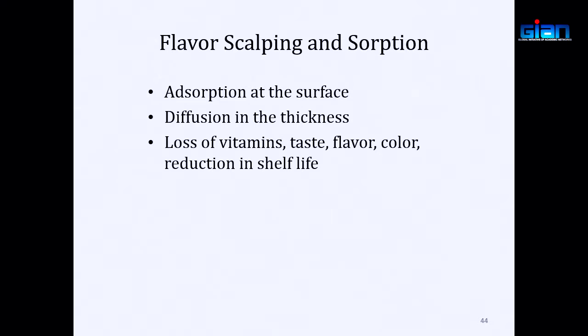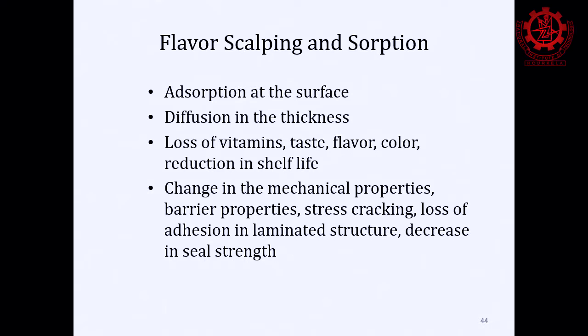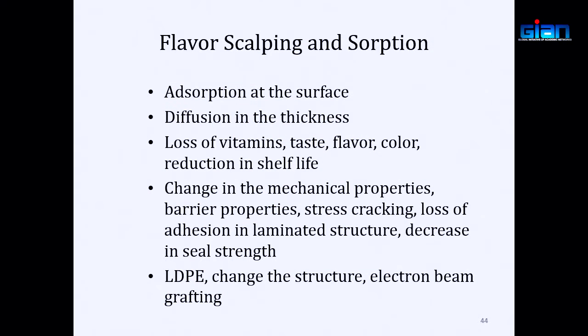Flavor scalping occurs when flavor compounds absorb at the film surface and diffuse through the film thickness. This can cause loss of vitamins, taste, flavor, and color, reducing product shelf life. It can also reduce seal strength, decrease adhesion in laminated structures, or cause delamination if oil or certain flavors are absorbed. Electron beam grafting on the surface is one method used to change surface chemistry and minimize scalping of volatiles and flavors.